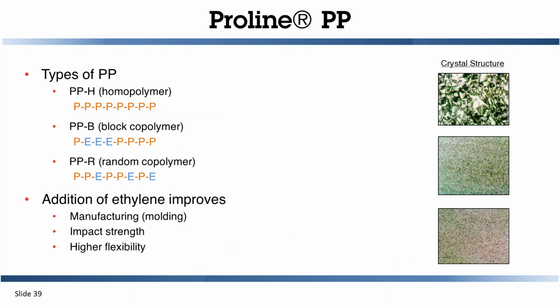PPB is a block copolymer, where a block of ethylene is added into the material. That gives added flexibility and smoothness. It's not really used for piping systems anymore. People have moved towards PPR, which has a similar concept. It has randomly injected ethylene into the propylene that gives it a more uniform dispersion and better strength than the block copolymer. On the right-hand side, you see a crystal structure, which is the surface finish under a microscope.